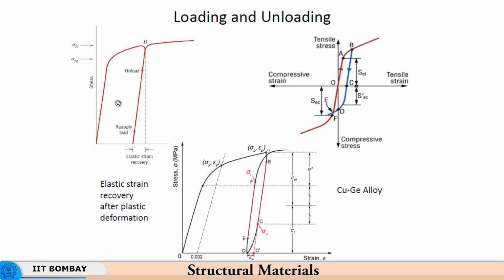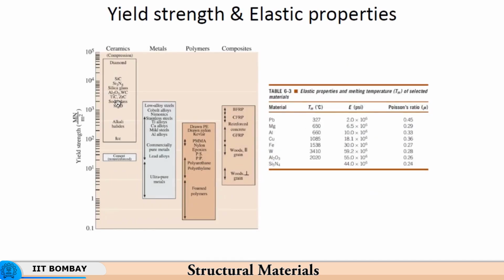This kind of elastic strain recovery is typical of certain alloys, and sometimes you see these things in samples subjected to fatigue, let us say axial fatigue or rotating bending fatigue, basically loading and unloading cycles, where so-called internal friction results in dissipation of energy, leading to a finite area of this loop, and therefore heating of the material during the course of fatigue. Now you see that the yield strength gets affected not only by the direction of straining, but also by temperature.